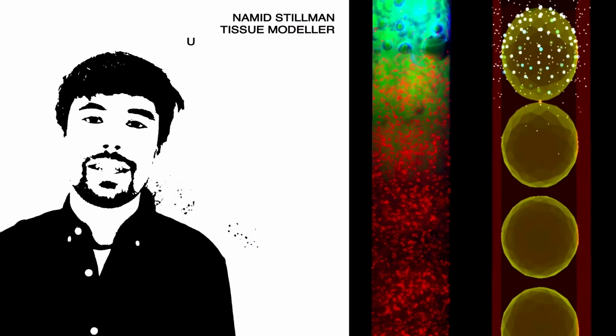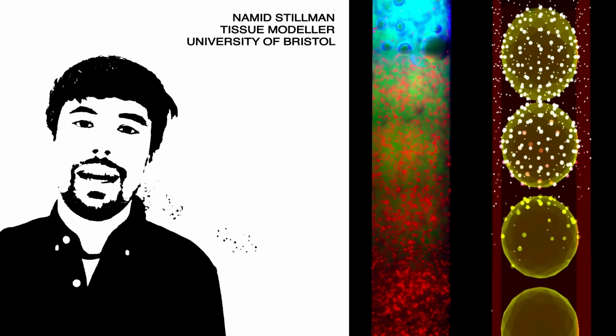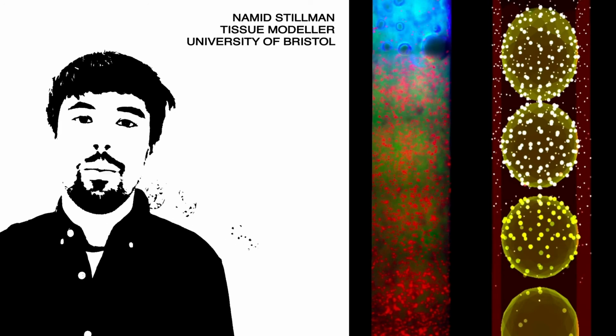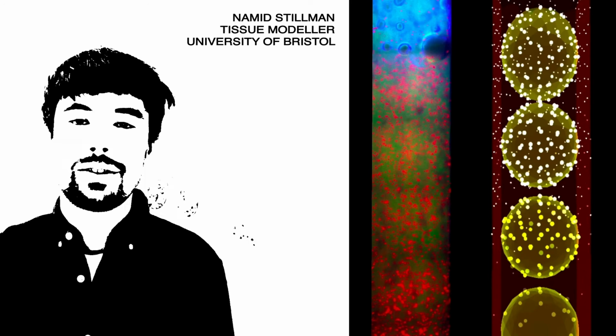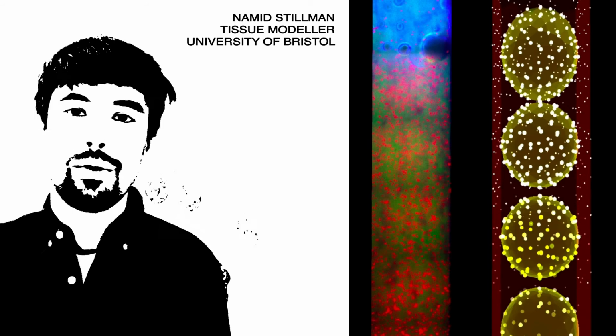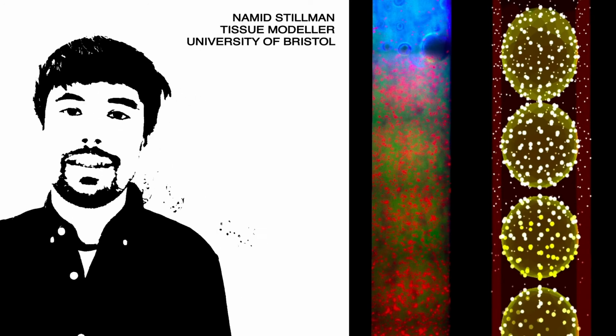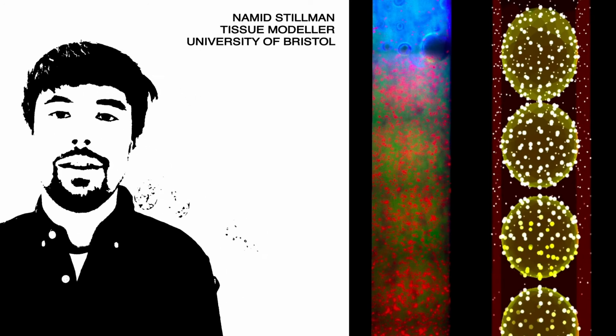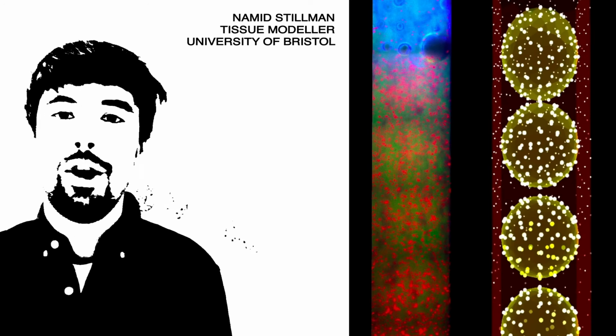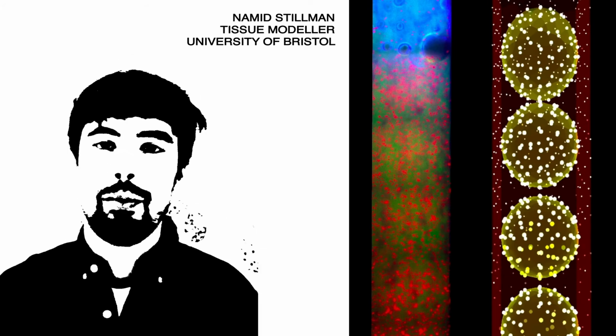We're using computer simulations to test how nanoparticle parameters impact their travel through tumour tissue. This includes things such as the size of the particle or how sticky they are, as well as how quickly they're internalized into the cell. We use a combination of agent-based models to work out how the particles travel through the entire tumour, to stochastic reaction diffusion systems to understand how particles move through subsections of the tissue. Right now we're interested in how space matters, that is, how tightly packed the cells are, and the material around the cells and the impact of that as the particles move through. We're hoping that these computer simulations accelerate the design framework and allow us to work out which parameters matter the most.